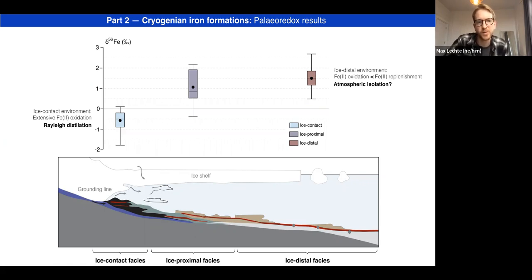And this is interpreted to represent distillation processes where you have extensive iron oxidation, removal of the heavy iron from the ferrous iron reservoir as you oxidize that out. And then eventually when you quantitatively oxidize the residual ferrous iron, you're going to be left with iron oxides that have this negative iron isotope signal. So this is indicating a greater extent of oxidation and therefore potentially high oxygen levels. And then if you look at the ice proximal facies, then that's transitional between those two.